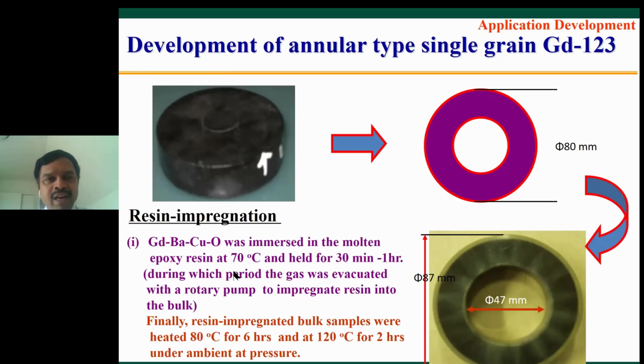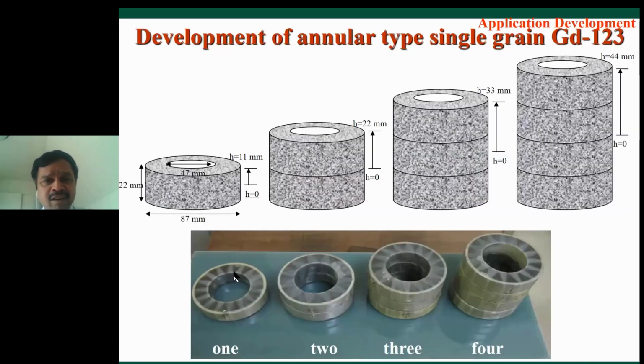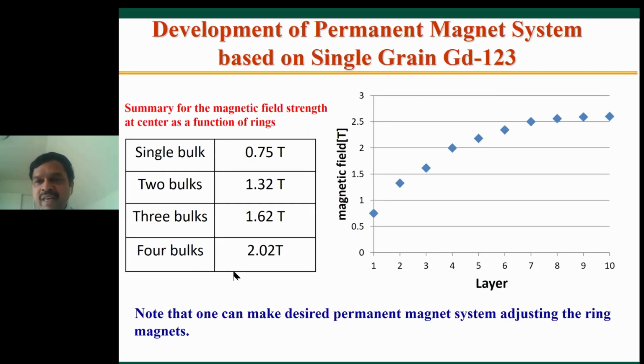And also we developed, using strong superconducting magnets, an annular type ring magnet. Here, one can arrange the samples in different shapes, like 1, 2, 3, 4. Especially, we found that increasing the number of ring magnets improved the magnetic field strength at the center of the magnet, which shows that these bulk ring magnets can be used as superconducting permanent magnets. You can see the left hand figure. If you use 4 magnets, 2.0 Tesla at the center of the magnet itself. But in the case of 10 ring magnets, it will be more than 2.6 Tesla.